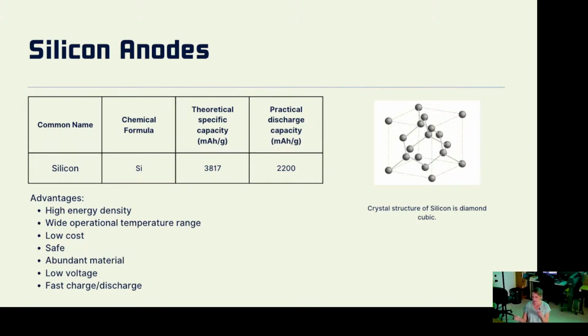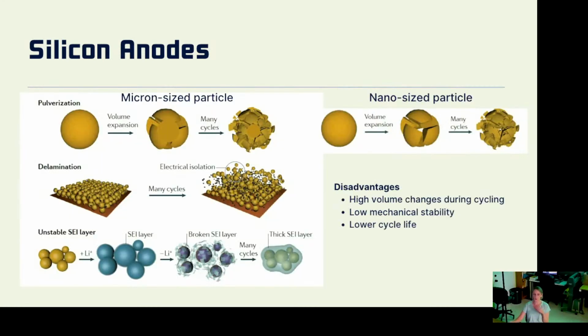But the challenge with silicon, though, is that when you do have the lithium going into the structure, it expands a lot. And if you have a battery in a package, if it's expanding a lot, then it could cause problems. It could swell too much and burst the container. So when you design a silicon battery, you have to make sure that your packaging is going to keep it intact.